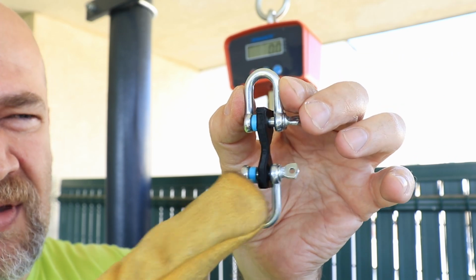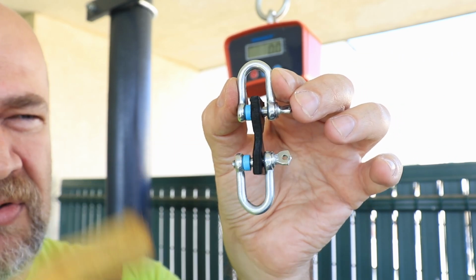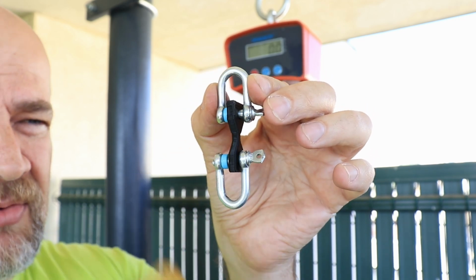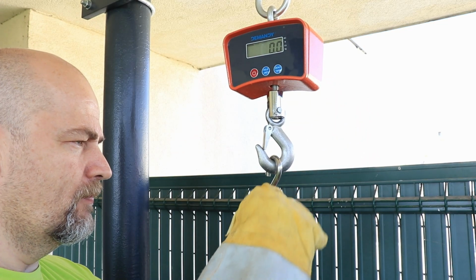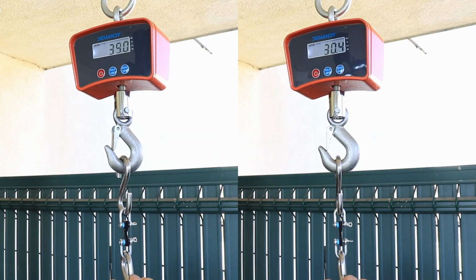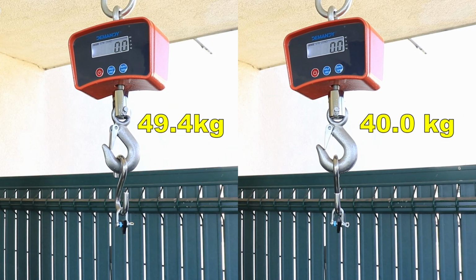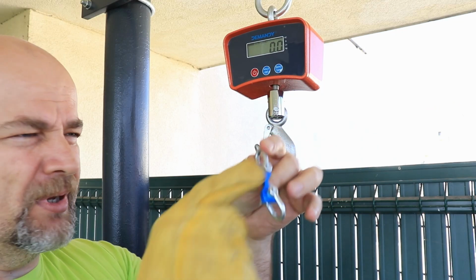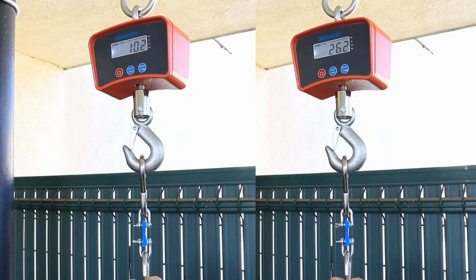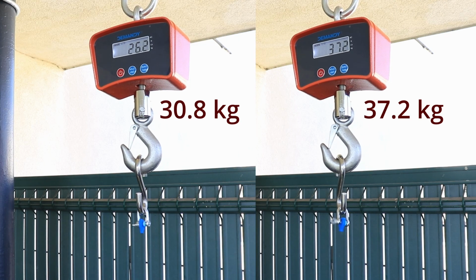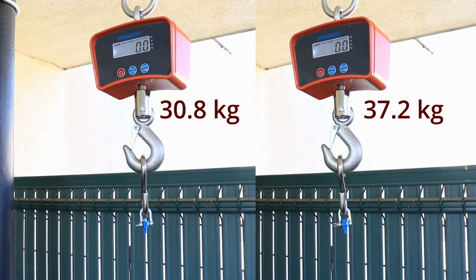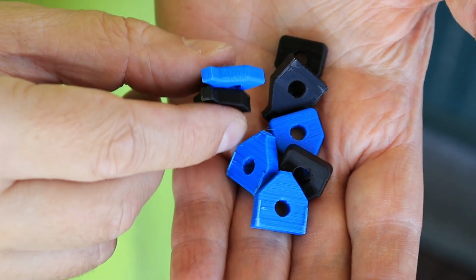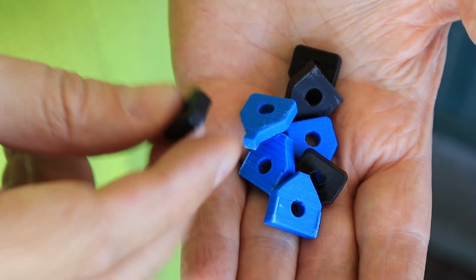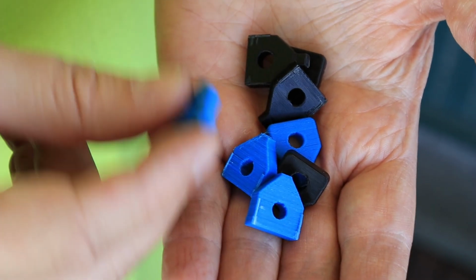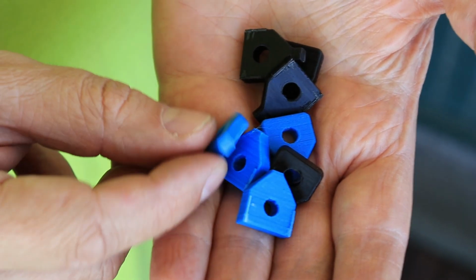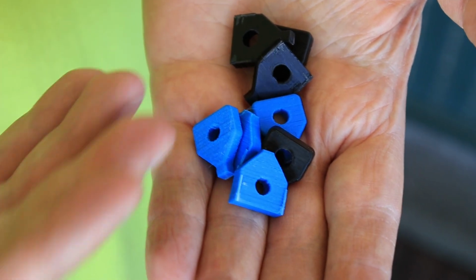Now the layer adhesion test, this test subject is printed in vertical position, and again the smallest cross-section area is 4 by 4 mm, and I'm starting with PLA Advanced. And now Engineering PLA. Well, they all broke properly on the smallest cross-section area. Even for the feeling, the PLA Advanced was stronger, but maybe I could raise the temperature with Engineering PLA, or maybe it is really better to print inside the enclosure. I'm not sure at this moment.